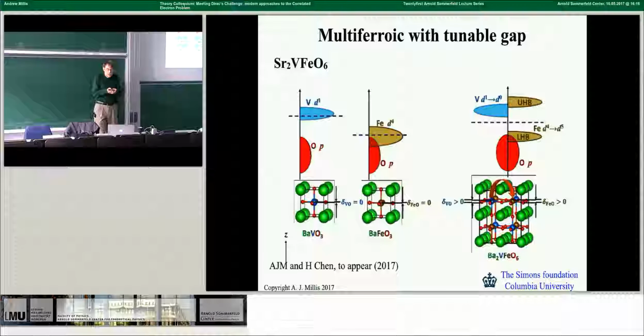Now, these things are interesting because to get a ferroelectric, what you want is an empty shell atom that is essentially not chemically bonded to its neighbors, so it's easy for it to move off of a central position. So the empty vanadium D shell will do that. And if the iron is D5, then the D shell is half filled and in a high spin state. And the half filled high spin D state is, for all practical purposes, like an empty state. The spin up half filled part is chemically inert. The spin down empty part is pushed up to a high energy by interaction so it doesn't hybridize. So this object is a multiferroic, and by playing games with lattice spacing and things like that, you can even control the insulating gap here.